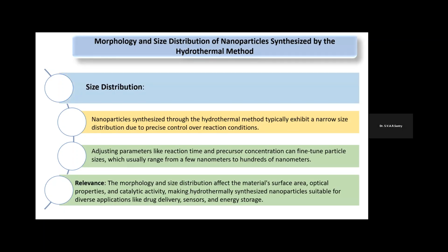Then coming to size distribution, the particles synthesized through this method have a good, very narrow size distribution, because we have already controlled the reaction conditions very precisely. Then adjustable parameters like reaction time and precursor concentration can fine-tune the particle size, which usually ranges from a few nanometers to a few hundreds of nanometers.